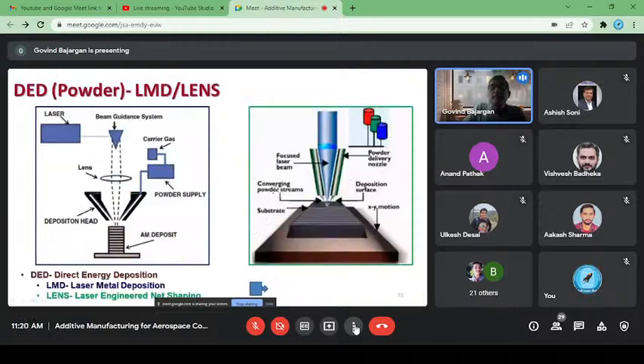In DED, direct energy deposition, there is an energy source. It can be an electron beam, or here it is a laser. It is DED powder which we are talking about. There are two ways by which powder can be fed. In the center we can have a laser source, and from the side powder is fed to the portion where the laser melts the base material, and this whole assembly moves as per the 2D sketch of the plane. It can be coaxial also. So either coaxial or from the side, powder can be deposited.